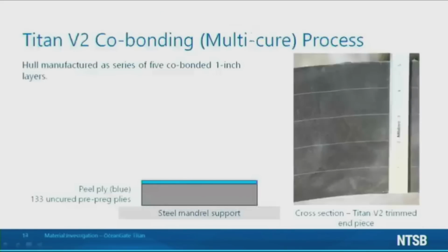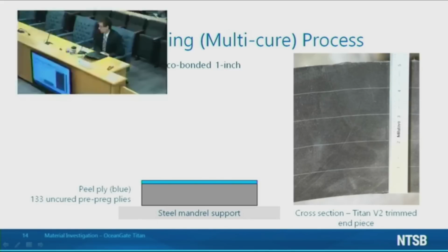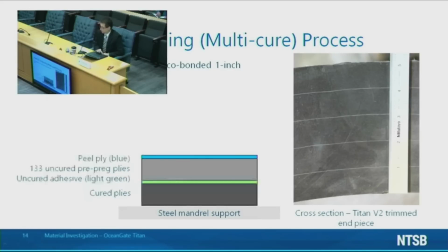The co-bonding process, or multi-cure process, as it was sometimes referred to by OceanGate, involved building up the composite hull in 1 inch layer increments. After the first inch of pre-preg was applied, the layer was capped by a peel ply. This peel ply was a plain woven synthetic fabric that was designed to be removed later. The assembly was then cured at elevated temperature and pressure in an autoclave. After curing, the peel ply was stripped from the surface.